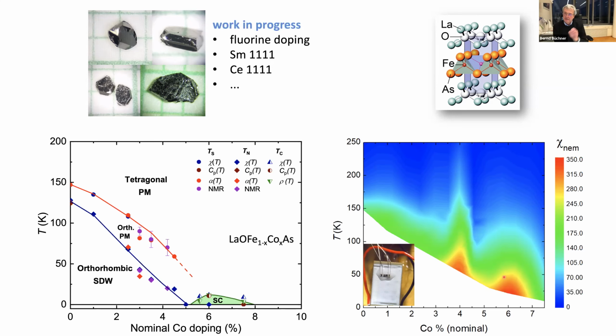Yes, it's an electronic instability, and also this surprising similarity. And I did not show you everything. I showed you only, let's say, the strain derivative of the Seebeck effect, which is identical for barium 122 and for these systems. You can have a look at the Nernst effect. It's identical. You have this completely different system, structurally completely different, a lot of different properties, scattering completely different. One is a nice metal, the other is a lousy metal close to localization.